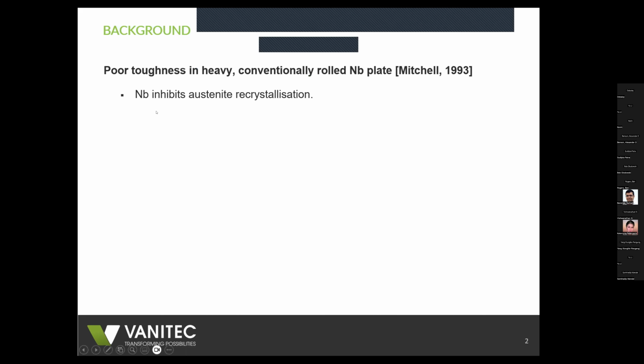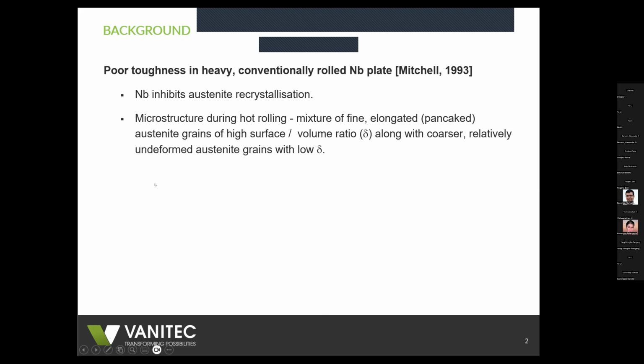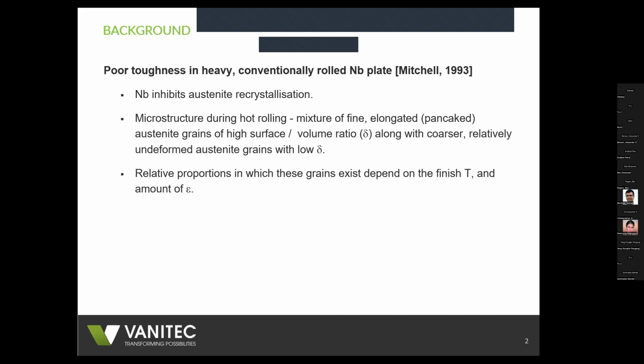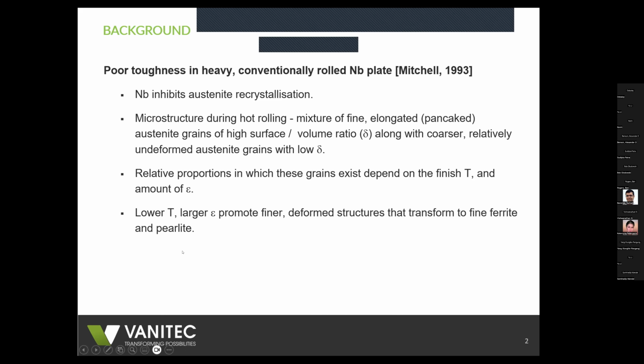niobium plate, and that's because niobium, first of all, inhibits austenite recrystallization, but the microstructure during hot rolling, and I'm talking conventional rolling, consists of a mixture of fine elongated or pancake austenite grains of high surface to volume ratio, or delta, along with coarser, relatively undeformed austenite grains with low delta. And the relative proportion of these depends on the rolling parameters, again, finishing temperature, the amount of strain applied, particularly below the TNR. Now, lower temperatures and larger strains would promote finer deformed structures that transform to fine ferrite and pearlite. But the opposite would be true for the coarse austenite.